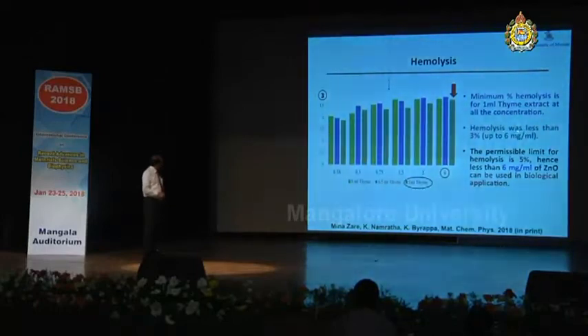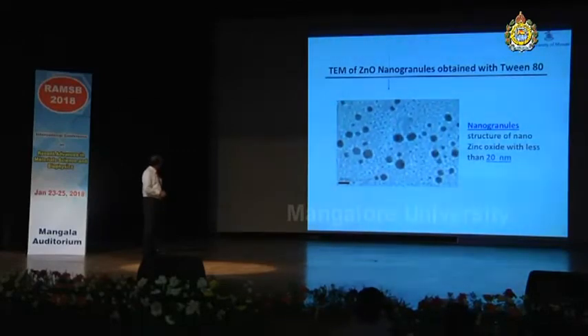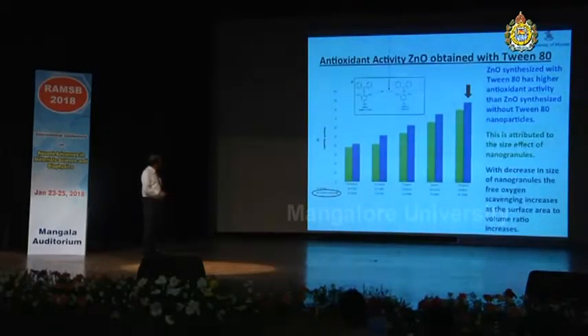In all our experiments we got hemolysis less than 3% up to about the concentration of 6 mg per milliliter of the zinc oxide. That's a good result. And these are the nano granules obtained in the presence of Tween 80. Without Tween 80, we have tested, we get bulk and highly agglomerated particles, and this is how we can control the morphology. And with Tween 80, we have also tested the antioxidant activity of this zinc oxide nano granules.